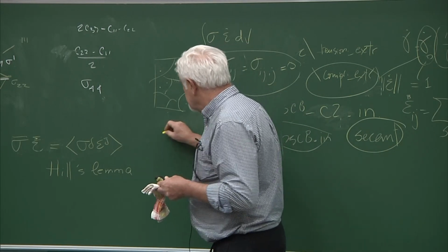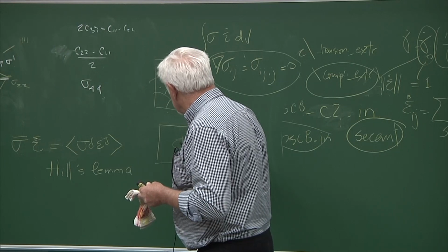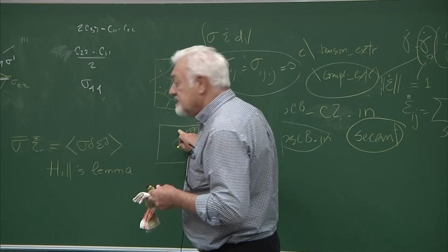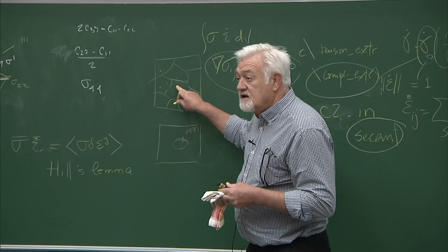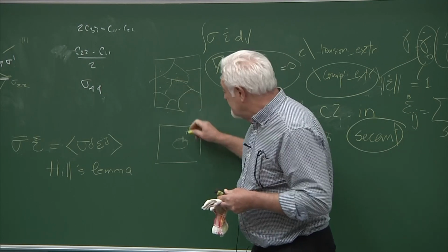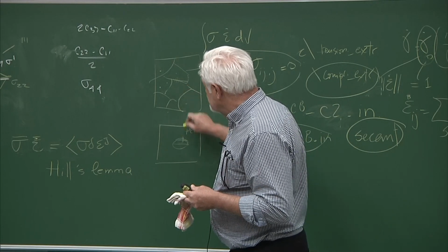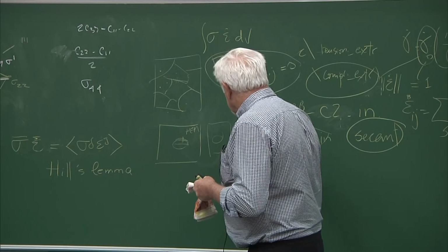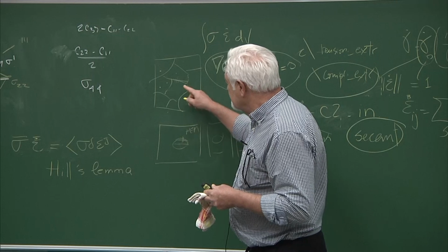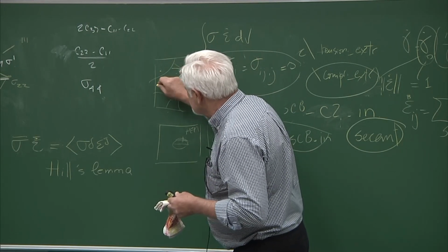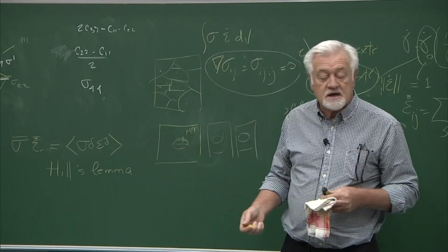The problem is that in our case, our grains verify that with a homogeneous effective medium, that across this interface they are in equilibrium with a homogeneous effective medium, but this is an average medium. It's not the real environment of each of the grains. So that is what gives us homogeneous stress in the grain. But the price that we are paying is that when we say, okay, I'm going to treat every grain as an inclusion in the same homogeneous effective medium, this is not really true if you think of this as being just homogeneous stress here, homogeneous stress here, homogeneous stress there. So you are going to have discontinuities in the stress. And so that is where the difference comes from.